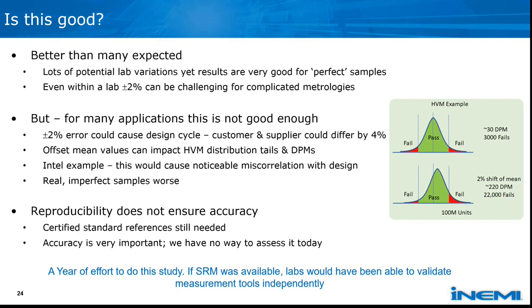Further, if your mean value of characterization of your material samples has an offset due to these metrological issues, that can impact high volume distributions and can push more material into the fail region of your defects per million outgoing quality controls. So within Intel, we would notice this kind of a miscorrelation with our design, and we would try and recenter it if we had this kind of an error.